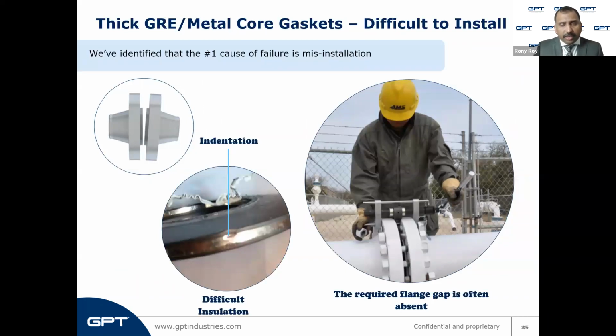Another big challenge with GRE laminated isolation gaskets is their thickness. The metal core GRE isolation gaskets, due to the limitations of the then available technology, were made thicker than the conventional gaskets. A metal core isolation gasket is 6.6 mm thick when compared to a 3.25 mm thickness of a regular gasket. This leads to the need for a different approach of installation, and the flanges need to be spread much more than the usual.